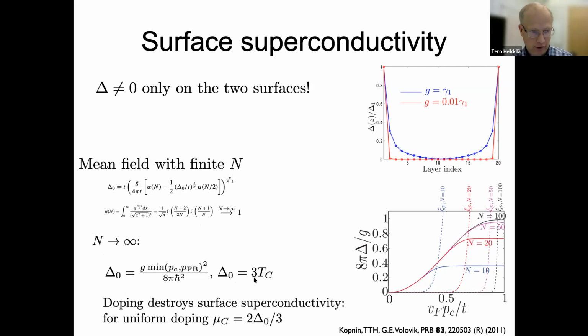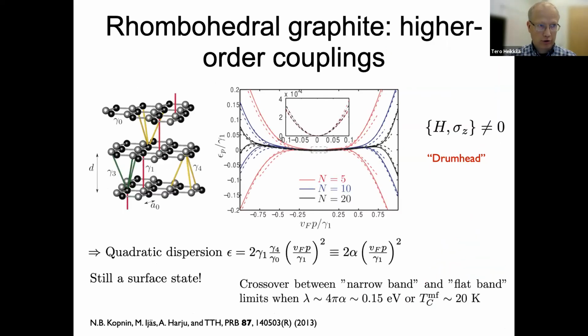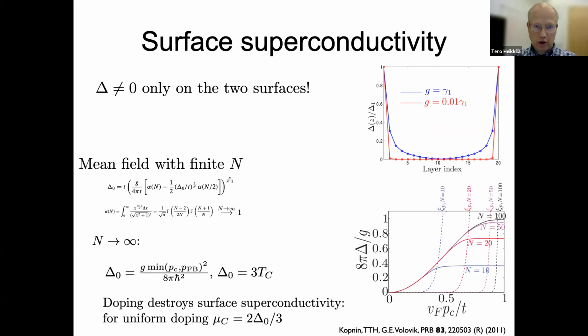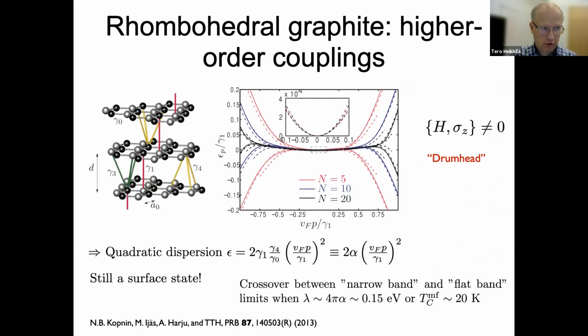So this is not the same factor as in usual BCS theory for Fermi surfaces. And you also find that doping destroys this surface superconductivity at a doping level that depends on delta. This was based on only taking into account this gamma 1 hopping, but you can also consider what happens if you have higher order hoppings.